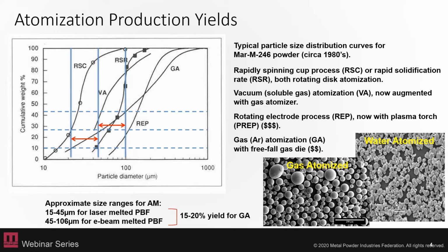So not only can you see the difference in size distribution, this is weight percent versus particle diameter. Your particle diameter is shifting significantly based on the process that you're using, but also your cost is changing. PREP is commonly known as the most expensive method to make powder, but it makes really, really high quality powder. But some of these other methods, such as free fall gas atomization, are maybe a little bit cheaper. But if you're using inert gas, that becomes more expensive than if you're using a water atomized process. If you're using gas atomized powders, you're getting really nice uniform spherical powders. However, using water to atomize and break up that melt stream, you get oblong, off-spherical shapes that are a little more jagged and non-uniform, which could have an effect on how you're able to process those.